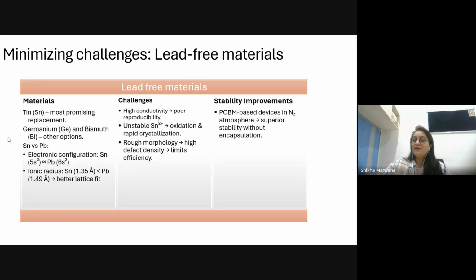Although with lead there is toxicity, stability and efficiency can be improved if I do hit and trials with ABX3 materials. Okay, sorry, A and X materials, because if I fix B as my lead, but if I use tin as my material, then it is less toxic to the environment, but then we have to compromise with the stability and the efficiency. Then improvements can be done when we make use of PCBM based devices, superior with the stability without encapsulation.